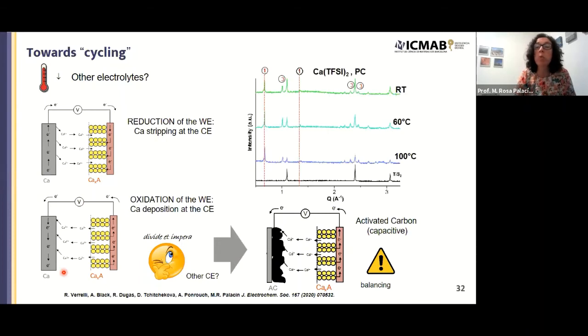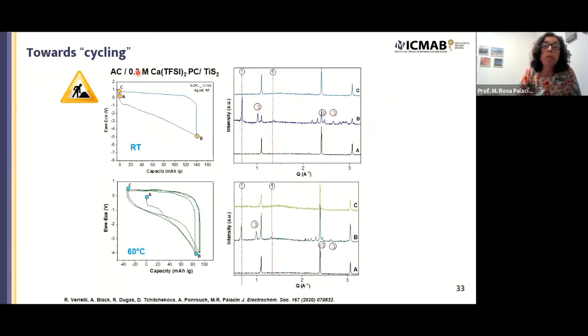But by doing this, we were able to see calcium intercalation into TiS2, even at room temperature, working with calcium TFSI as electrolyte in propylene carbonate. And we don't see the phase number 2. So in this case, with this electrolyte, only phases 1 and 3 are formed, which is something we're still having a look at. You see that we can do even some cycling at room temperature. Polarization is still huge, so there is still a lot of things to improve, but we are currently working on that.